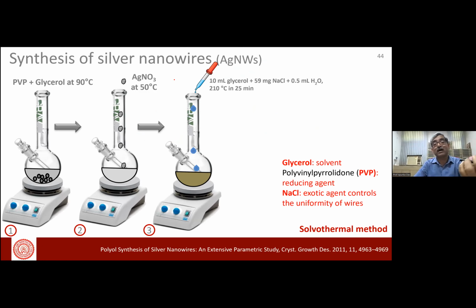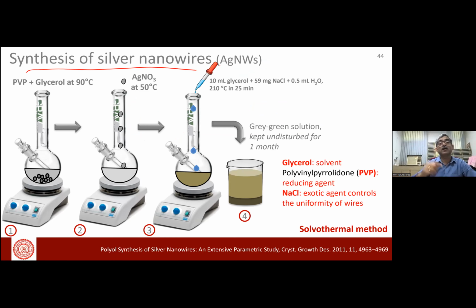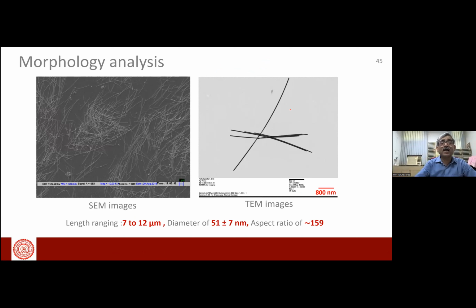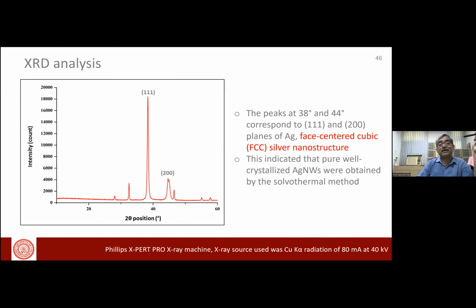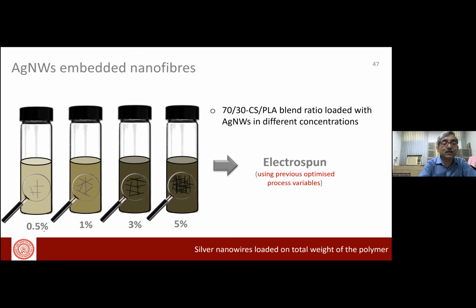There are standard methods to develop the silver nanowire. We have optimized it in the laboratory, and you can see these are the silver nanowire, with the length ranging from 7 to 12 micron and diameter around 50 nanometer. This silver nanowire is embedded inside the nanofiber. We have used 0.5%, 1%, 3%, and 5% nanowire mixed with the chitosan and PLA.